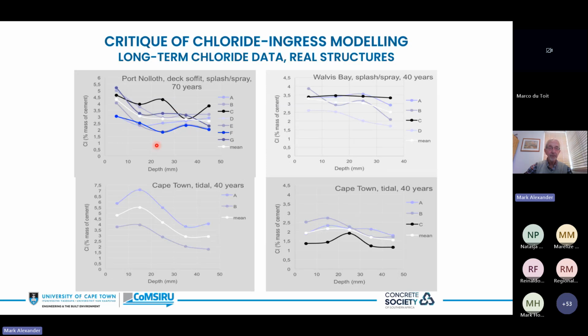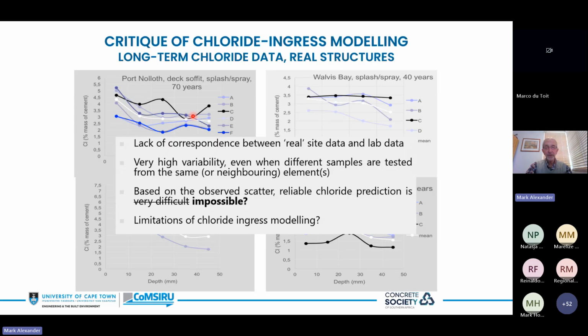And these are samples taken from very close to each other. So they're not from vastly disparate structures. They're from relatively closely spaced or closely sampled sites within these structures in hand. So the variability is huge. And that's something we have to, again, grapple with. So there's the lack of correspondence between the real site data and the lab data. Easy to work in the lab, much more difficult on site. Very high variability, even when different samples are tested from the same or neighboring elements. And based on that scatter, can we really do reliable chloride prediction?